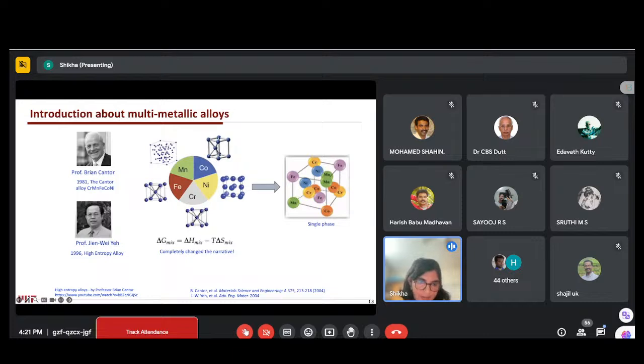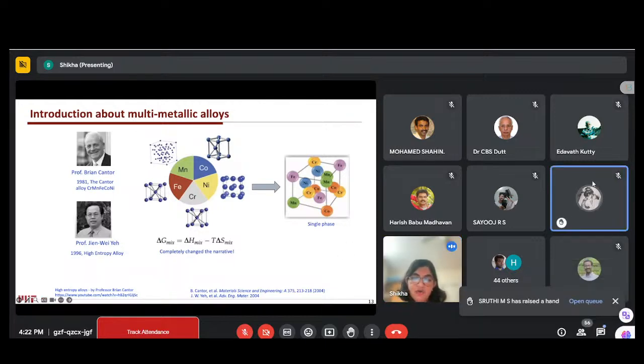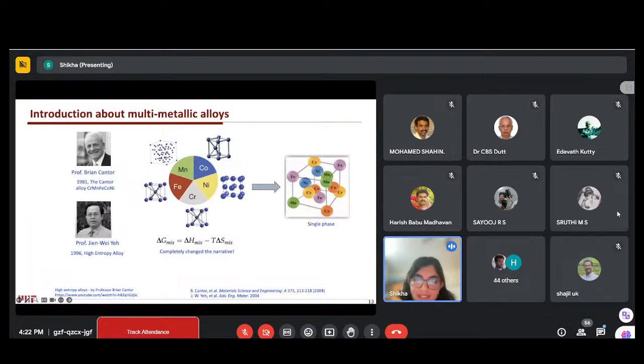At the same time, Professor Yeh was also working on this, and he named them high entropy alloys, because the formation of a single phase with so many atoms arranged randomly within it is driven by the high entropy change, which leads to the formation of a stable phase of high entropy alloys. So here we took different metal atoms with different structure symmetry, but they could form because of the high configurational entropy of the formation of the materials.